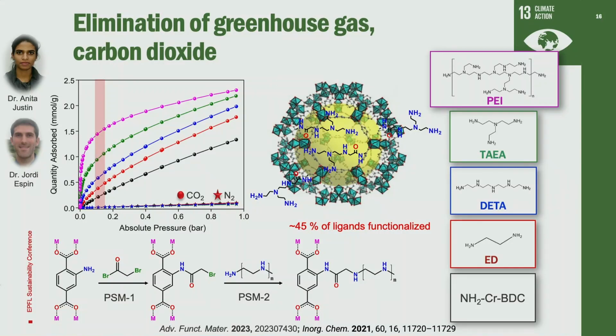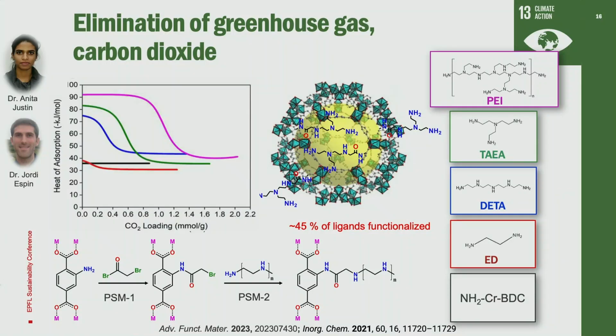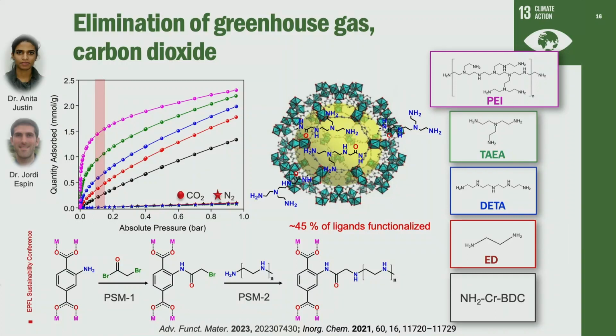So we took our material. Here you can see it has this functionality here, which is also an amine. We use this bridging molecule. It binds to it. And then we can graft the amines inside the material. So now they're completely immobilized. When we do that, you can see here our starting material that's not modified in black. Then as we add amines to it, you can see this one here, it's a low molecular weight PEI. We see a huge increase in the amount of CO2 that it can take up, okay? If you look, this is showing you the quantity of nitrogen.